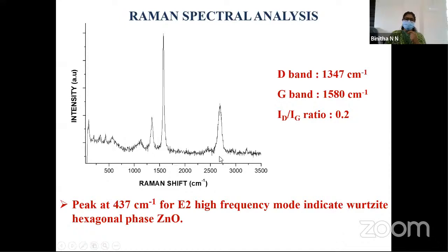The Raman spectroscopy result indicates the less defective nature of the prepared graphene. The ID by IG value is an indication. This is the G band, its intensity is IG. This is the D band, its intensity is ID. The ratio is less than 0.5 and it indicates the less defective nature of the graphene sheets. And there are peaks at less than 1000, and these peaks correspond to the presence of zinc oxide. So the formation of a good composite is also well established here.